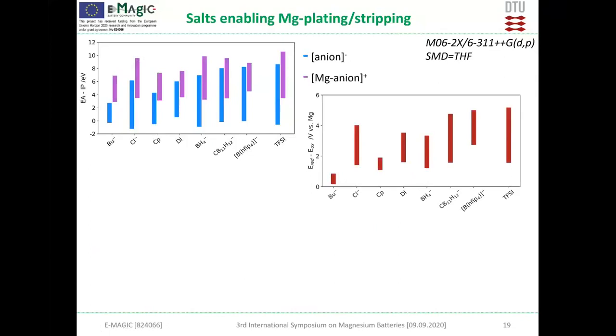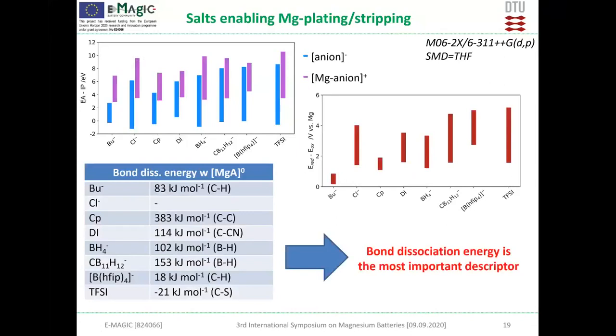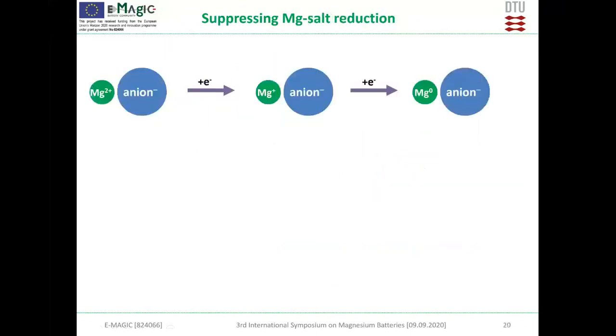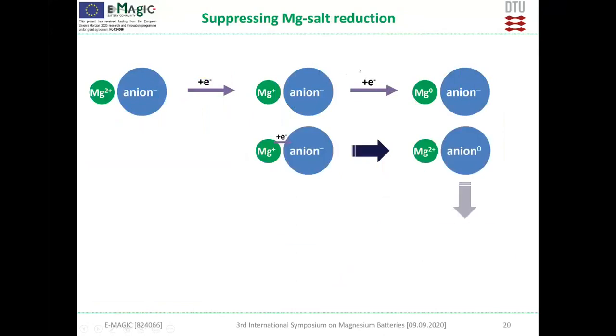So we went through many different descriptors. And finally, we found that the bond dissociation energy in the reduced form of this cluster can serve as a very good indicator if the salt will provide reversible plating stripping. You can see for all of them you have a positive value, and only for TFSI there is a negative value. And why does this descriptor work? Probably because when we reduce magnesium and want to plate, we are going through this metastable magnesium plus state. And we want, of course, to reduce it more, add more electrons. But what can happen is this super reactive species will react with the anion, and we will see the decomposition product.